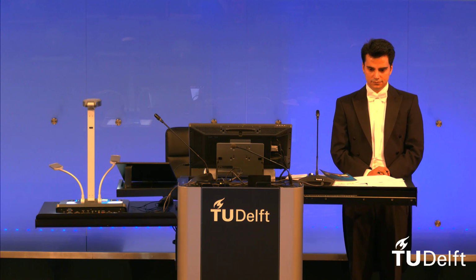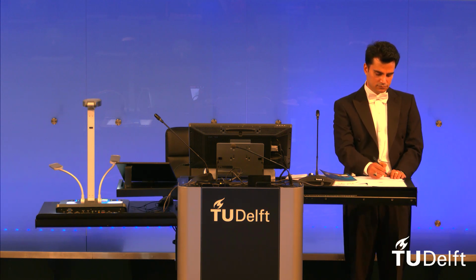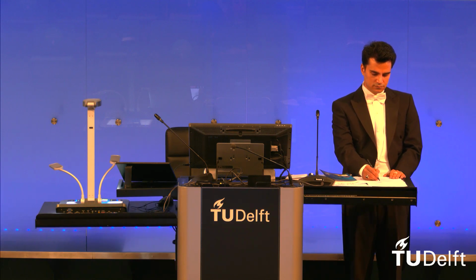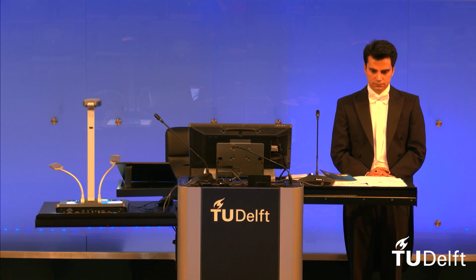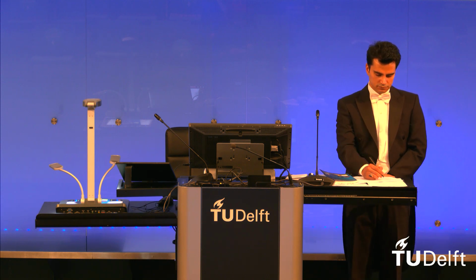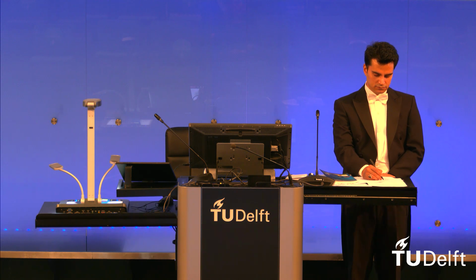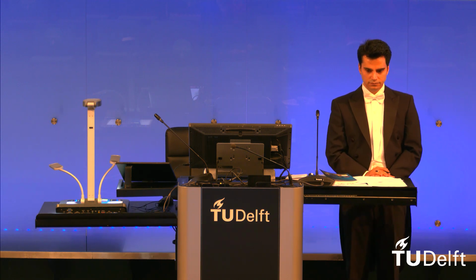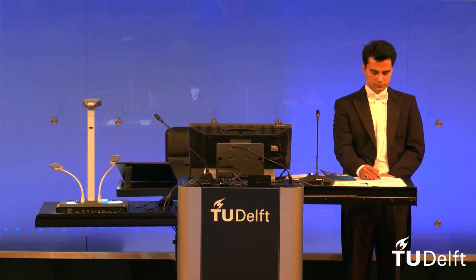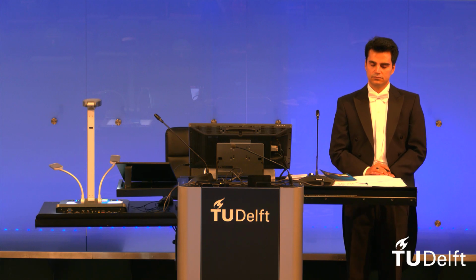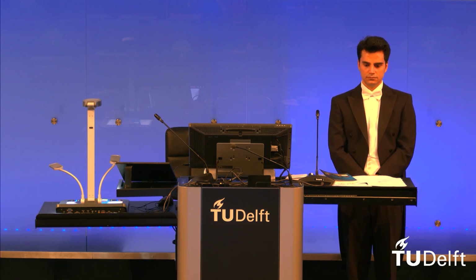The steel we're using for real industry at this stage is predominantly pearlitic rail steel, which contains almost 100% pearlite. So we understand that during the wheel contact, the temperature will rise at the surface of the rail, and so it may trigger the phase transformation during service. Have you measured the phase transformation temperatures of your steel, say for example using a dilatometer or other technologies?